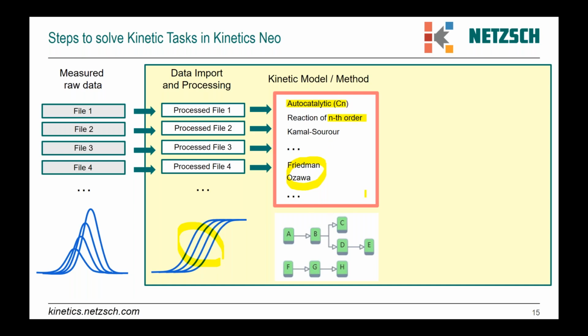During this application of kinetic method or kinetic modeling, we have finally one model or one mathematical model which can describe all experimental curves. So for 4 curves, we have not 4 models, but only one model. And this model has temperature and time as a parameter, and all other things like activation energy or order of reaction are the kinetic parameters.